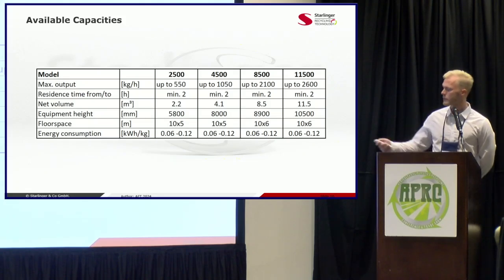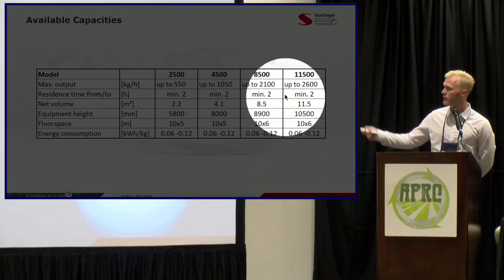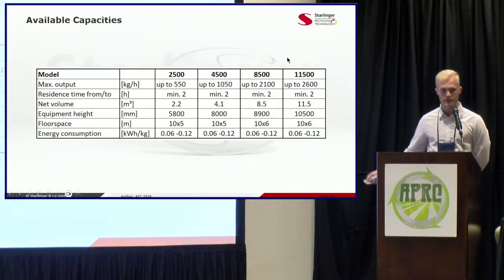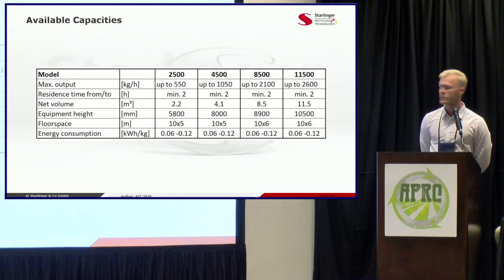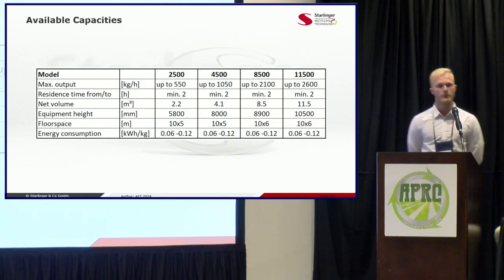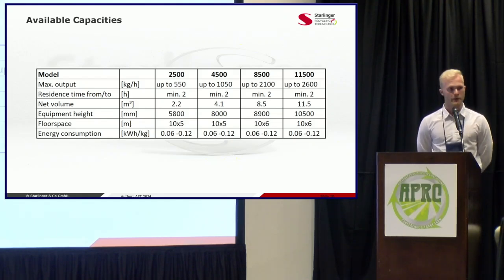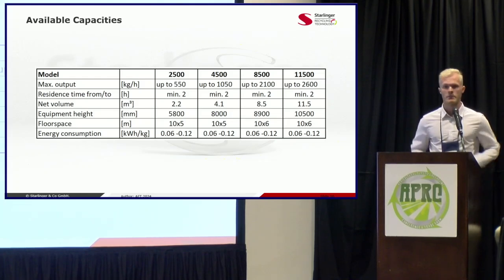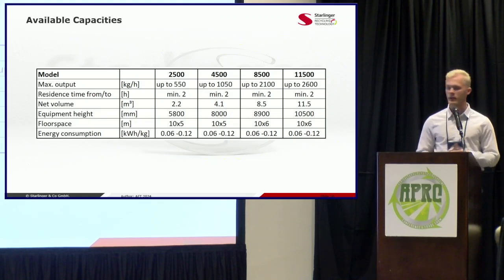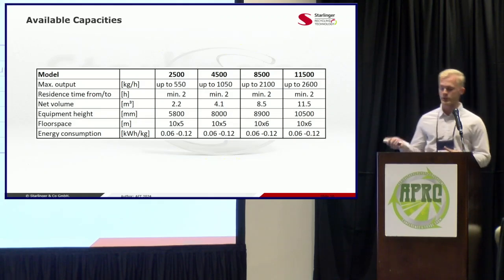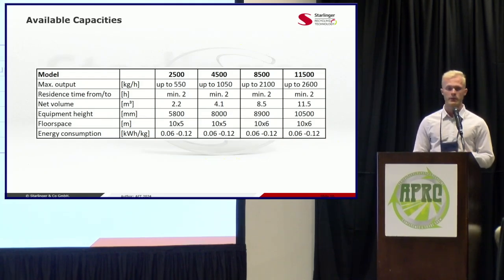But with these outputs, we've added the 11,500 unit, and this is 11,500 liters of capacity. So really for our 2 to 2.5 ton extrusion lines, because previously the 8,500 was the largest size, but sometimes customers would need 2 of them in line to keep up with the output. So we're always listening to customer needs and of course then evaluating future solutions on that. And this isn't, let's say, a faraway pipe dream as well. We actually have 2 of these 11,500 PCU Plus units located at a recycler in Mexico, so it is already commercialized.